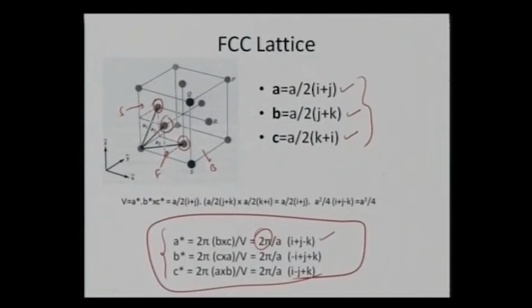So I can see that the reciprocal lattice of FCC is equal to BCC, and the reciprocal lattice of BCC is equal to FCC. So that shows a correspondence from the BCC to the FCC lattice: simple cubic remains simple cubic, but FCC becomes BCC in reciprocal lattice spacing.